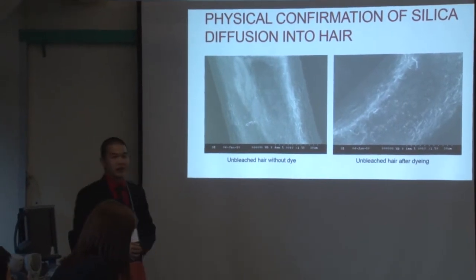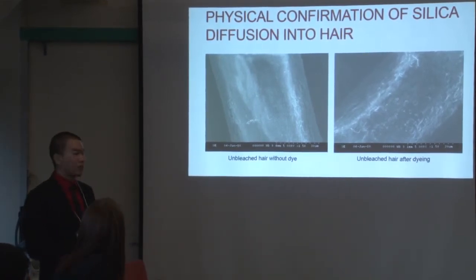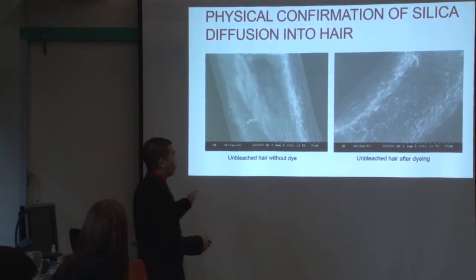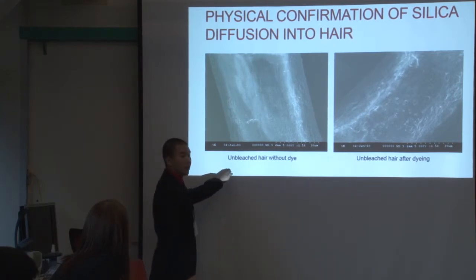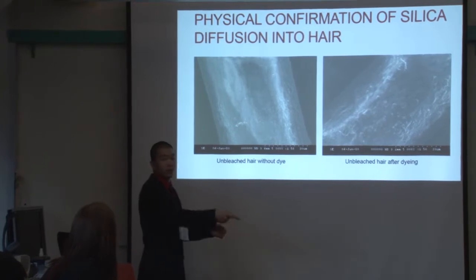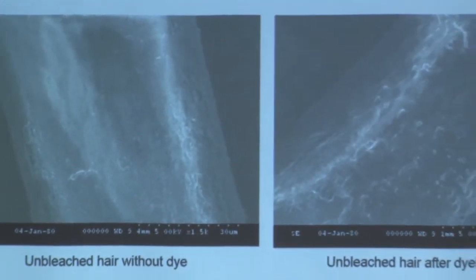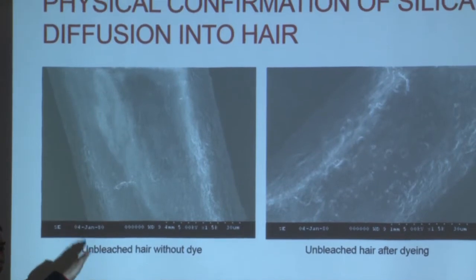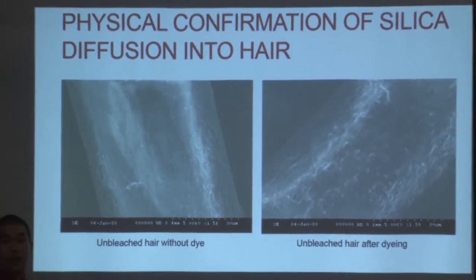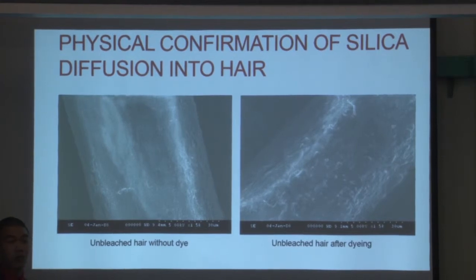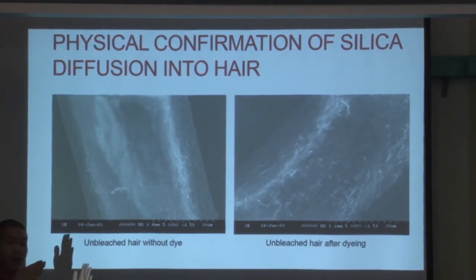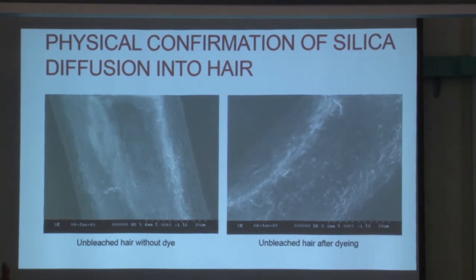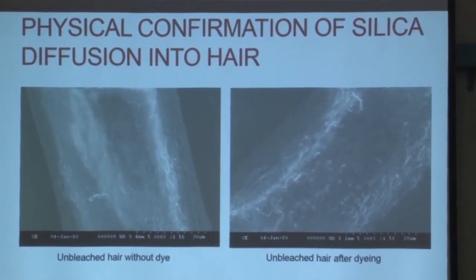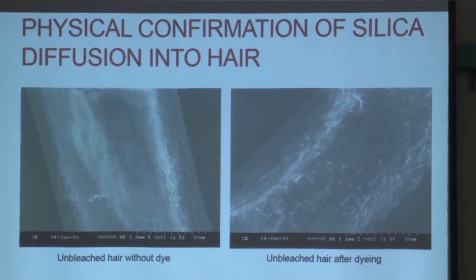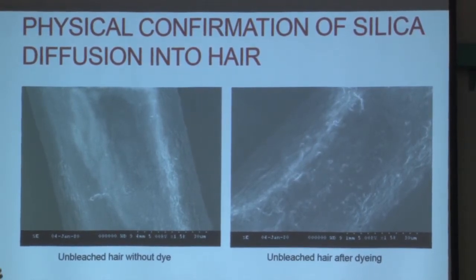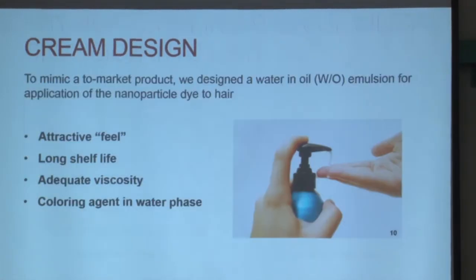So to round off our battery of characterization tests, we also took a picture of the surface of the hair before and after dyeing. This is unbleached hair without dye, and on the right side we have unbleached hair after dyeing, the hair that you just saw. As you can see on the left side, the hair surface is very smooth, indicating that it's a very healthy specimen of hair, because if it was unhealthy, it would have increased cuticle raising. On the right side, we can physically confirm that the particles have diffused on the hair surface, which causes the rough surface which you observe in this picture.